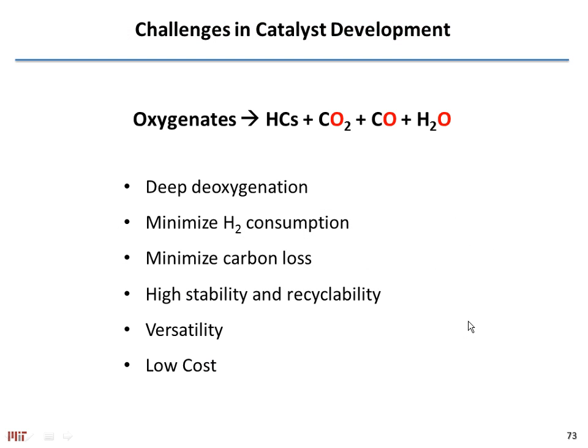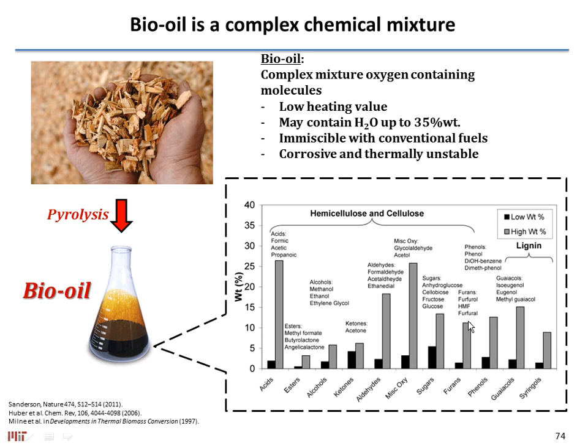So from there, you can imagine that you would want sort of a dream catalyst that would do a deep deoxygenation, kick out your oxygen in the only three ways possible: CO2, CO, or water. You want to minimize your hydrogen consumption, minimize carbon loss, or at least keep the carbon chain length of your starting molecules, if not increase it. It should have high stability and recyclability, of course, and low cost as well. And this is obviously a dream list, because we would all like to have catalysts like this all the time, but it's very rare actually to find them. Whoa, I didn't know I had that animation there.